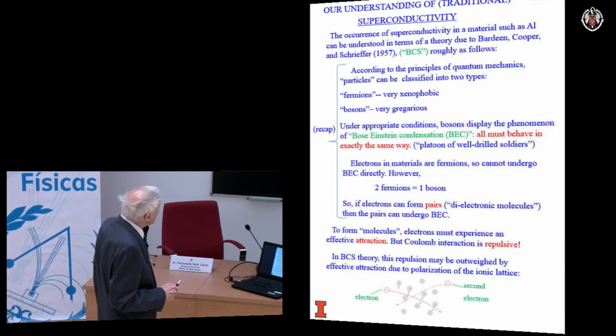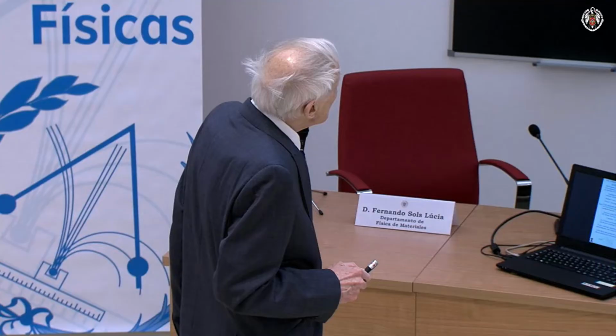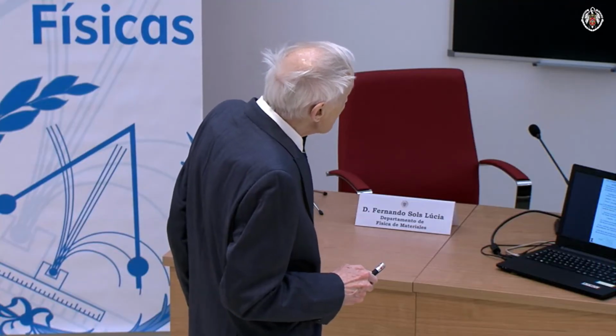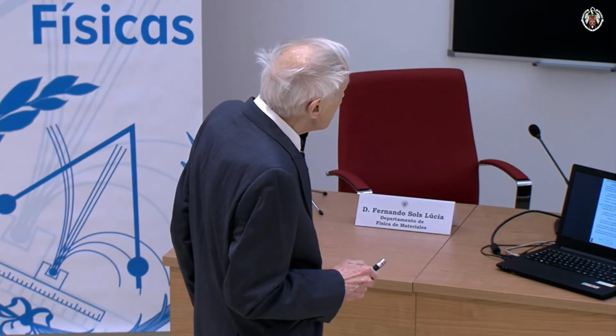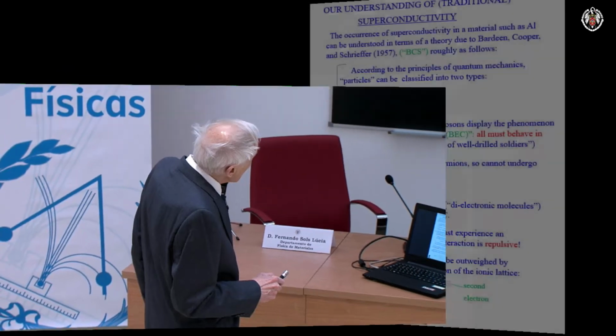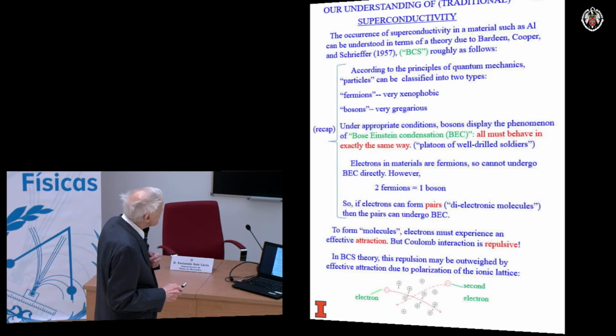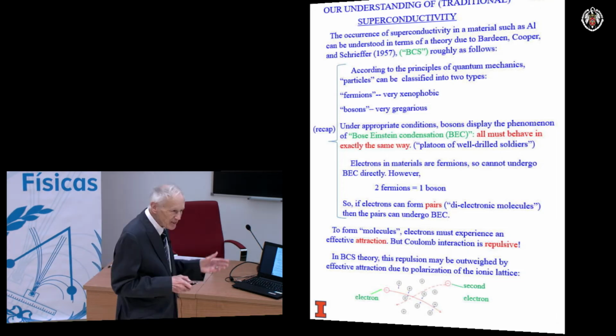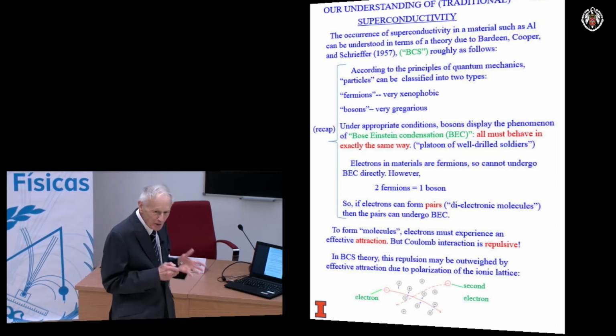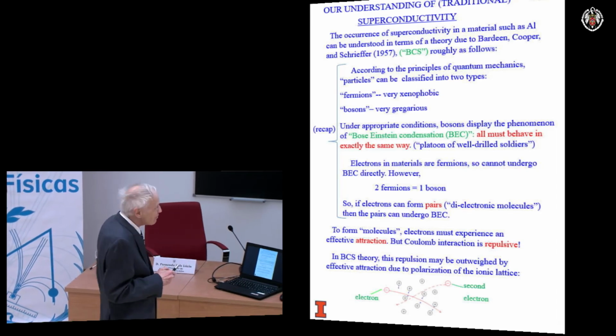Now, to form dielectronic molecules, initially you have a set of ions which are positively charged sitting around at these points here. Electron number one comes through. The ions are attracted towards it, and the region through which the first electron passed becomes positively charged. And so you get an effective interaction, an effective attraction between the two electrons themselves, and the second one then sort of tends to fall into it. So you get an effective attraction between the two electrons, and basically that's roughly what's going on here.